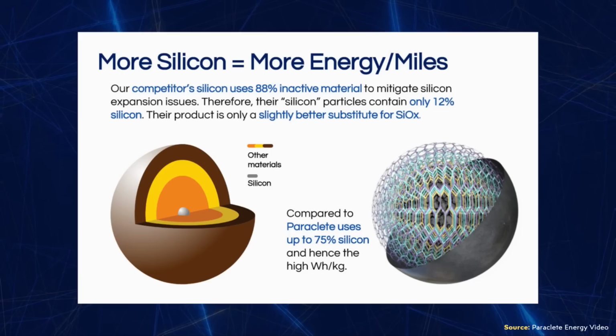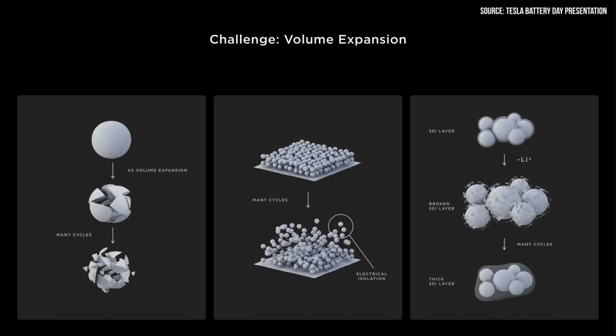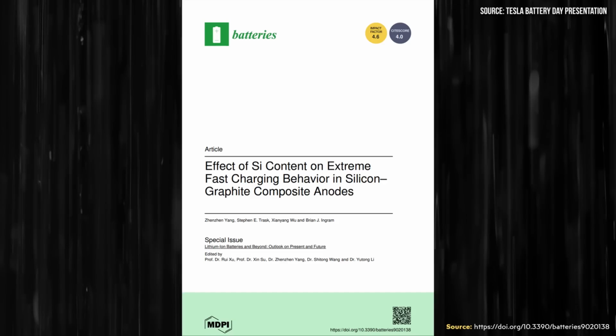Their approach creates a polymer silicon matrix that increases the amount of silicon in each particle from around 12% from a typical carbon-based matrix to around 75% with their polymer silicon matrix. In addition, as I will discuss more shortly, even in amounts as great as 15% of the anode by weight being silicon, the normal expected cracking that happens during volume expansion of silicon in high amounts in an anode doesn't appear to occur with Paraclete Energy's product, according to a finding published in a scientific paper.